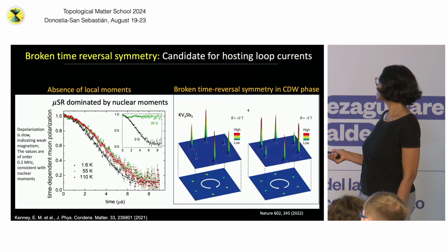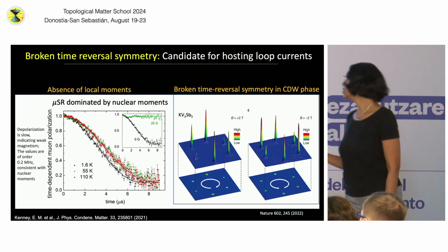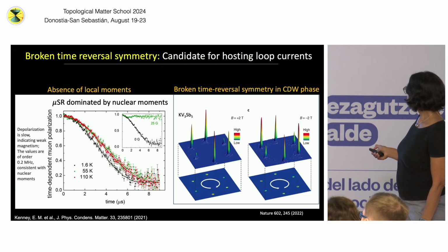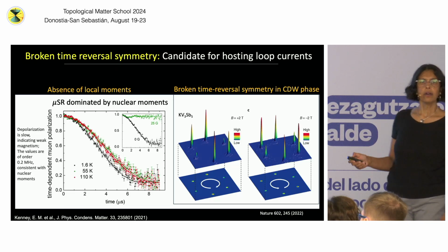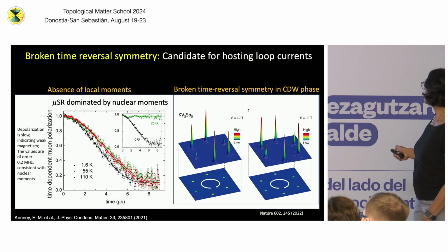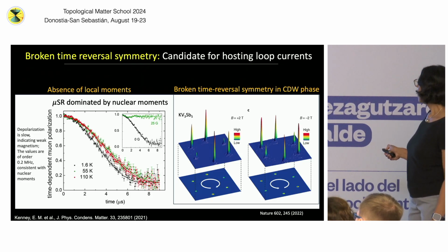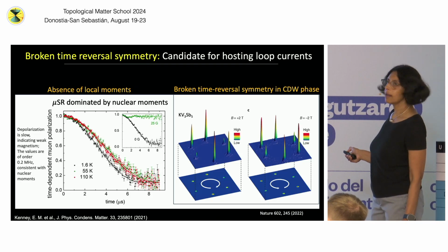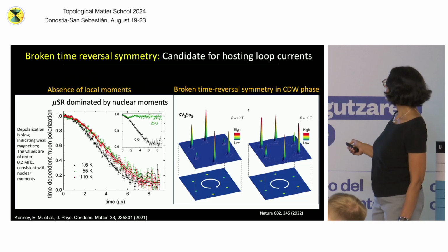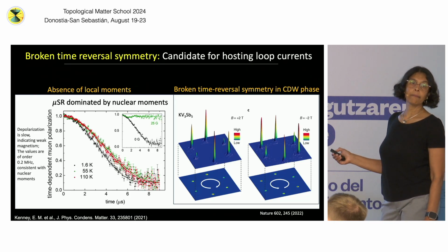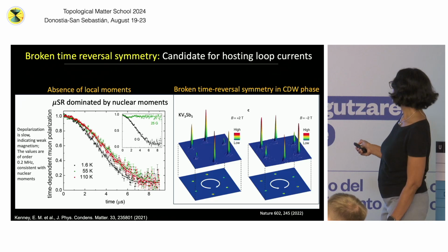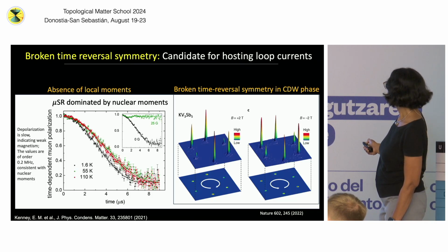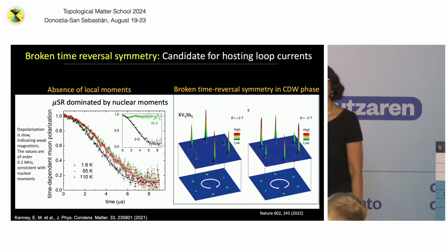And so this material has a charge density wave order below about 200 Kelvin, okay? And these peaks that you see here are the Fourier transform of a topography in STM. So these are the charge density wave peaks in the Fourier transform. What he showed is that, I think Stephen and Ming talked about this briefly, you can manipulate the relative intensities of these charge density wave peaks using a magnetic field. Okay, so you can see here in this, for +2 field, this is high and this is low. And in a -2 field, it's the opposite. This becomes this, it's high, and then this is low.